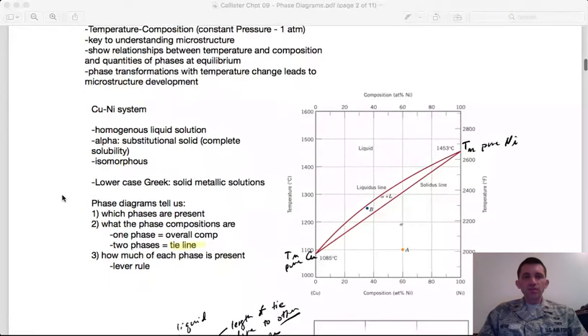So phase diagrams of this type are key to understanding microstructure, because they show what phases we can expect to get at various temperatures and compositions, which is going to be key to tailoring our material properties, right? So what composition do you pick and what temperature do you process it at? You're going to make those decisions based on understanding of the phase diagram.